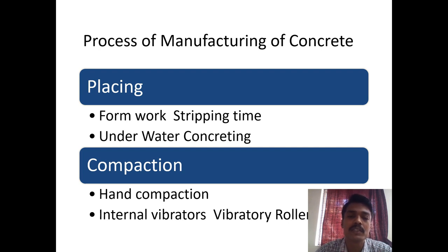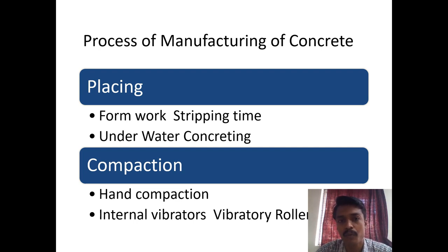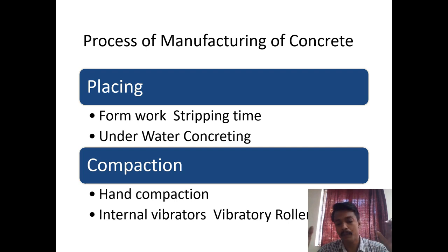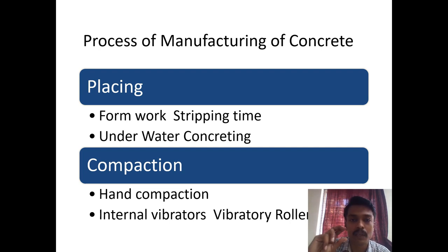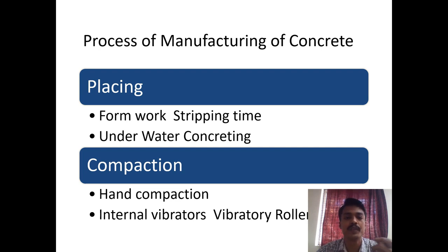In smaller residential projects, especially in columns, people mix all the concrete and completely pour it in, so only the top layer gets compacted well. In one site observed two months back, for almost one foot at the bottom of a column, honeycomb was witnessed. That is because of poor management on site as well as poor compaction.